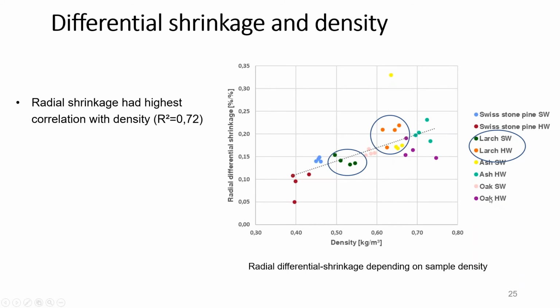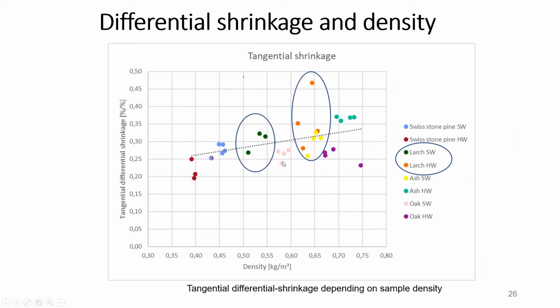And other species, like if you look at the oak, this is the oak, softwood, and these dark purple ones, the pinky ones are the softwood, and the purple ones are the hardwood. Also quite interesting how they are distributed. So this is the radial shrinkage, which had the highest correlation with the density. Another example is tangential shrinkage. Not as well correlated with density, but still, you see here the larch softwood and hardwood, also different in density, but not so expressed in the tangential differential shrinkage, because it's just not showing up for structural reasons. Quite interesting to argue why that is the case.